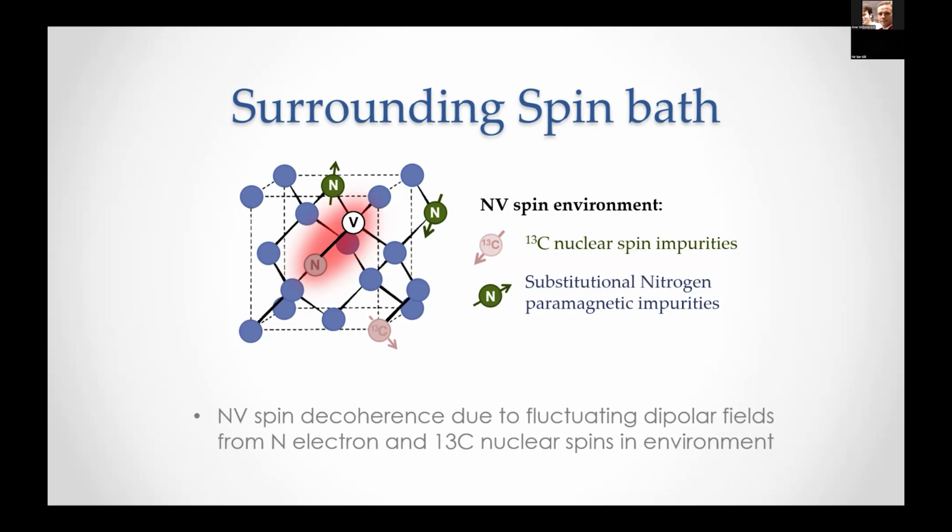For us to get the vacancies to relax the structure and not create deformations, which also happen, we tend to anneal our samples, basically heat them up in vacuum at around 1,000, 1,200 degrees C to help the structure relax. But there are always things that are still in there. Carbons that are not in the right place, all kinds of grain boundaries or things like that.